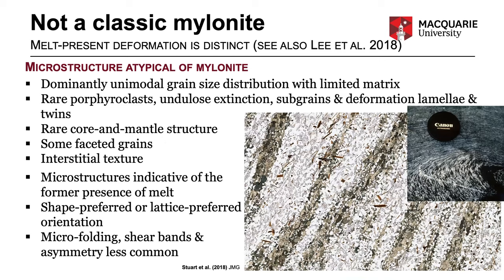The microstructure of melt-fluxed high-strain zones lack the bimodal grain size distribution and most other features common to typical mylonite. I think the characteristic microstructural observations from our study listed here are an excellent indicator for shear zones and sites of former melt flux through the lower crust.